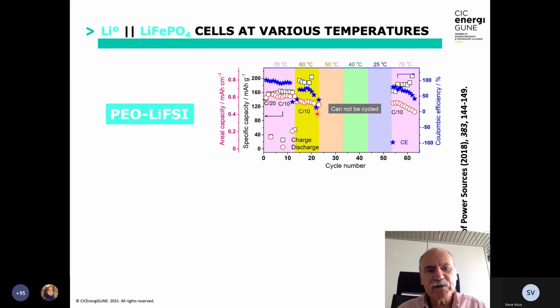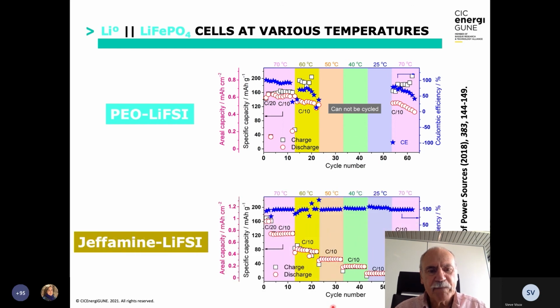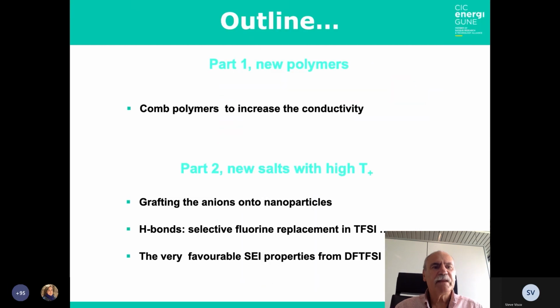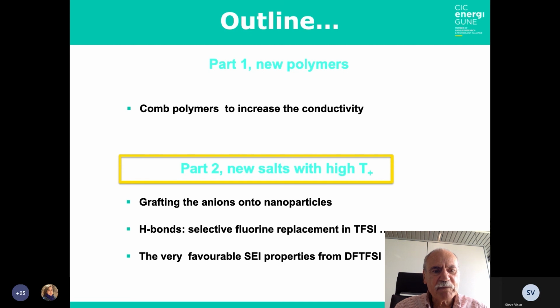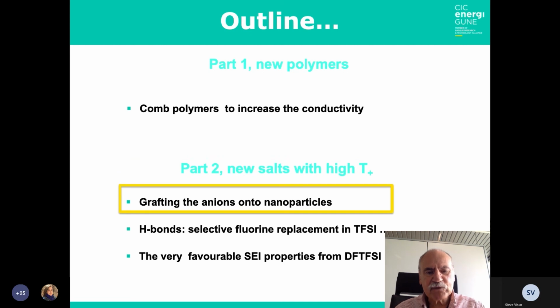Of course, if you cool down, you don't operate the battery and warm it up, you can, when you reach 70 degrees again, the battery is not degraded and can operate. If you use a Jeffamine polymer, as you can see, even if you cool down the temperature, you lose in capacity, but the battery is still operative down to 25 degrees, though of a low fraction of utilization. But this means that it is not hopeless to think that polymer battery could work at close to room temperature, possibly 50 degrees. Let's go to the second part of the polymer, grafting anions onto the nanoparticles.